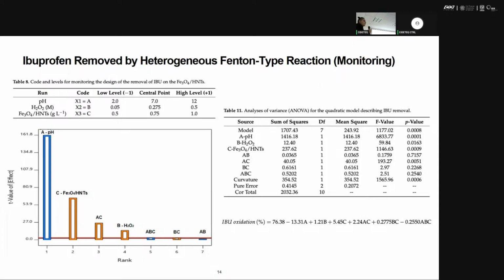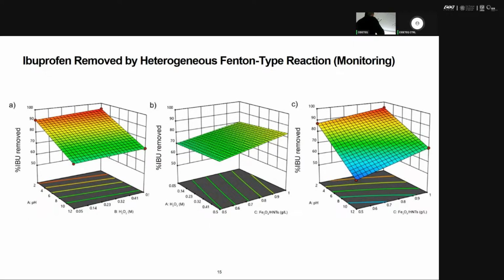And the usefulness of this kind of statistical method is not just to analyze every variable, but to analyze the variables combined. For example, AC means a combination between pH and absorbent material. It means that the absorbent is affected by the pH because it could be protonated. So that's why it's present here. It tells us that for a better absorption, the nanomaterial must be protonated in the acid system. So that is the advantage of this kind of model.